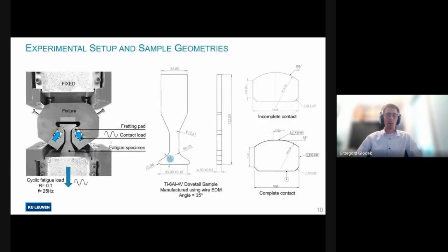Now the experimental setup is shown here on the left. So the stainless steel fixture holds fretting pads, which are made from wrought TI-64, and those represent the disc in the turbine assembly. Now, the application of a cyclic fatigue load to the sample generates cyclic forces in contact and cyclic relative displacement between the sample and the pad, which creates fretting fatigue conditions there. The geometry of the sample is also shown here. The most important part here is probably the skew angle, which is chosen to be 35 degrees.